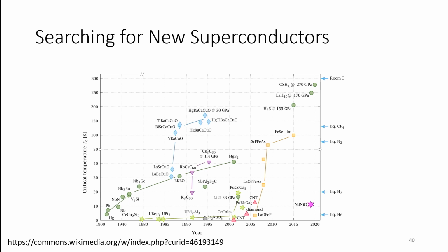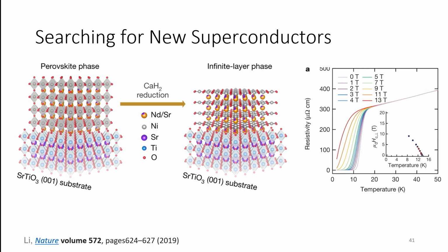So there's been a lot of progress over time, and there's been some really good work from the Mundi group here in discovering superconductivity in this nickel-based compound, which wasn't known to exist before. One of the tricks there was, neodymium nickelate has a perovskite structure I showed you previously. It was discovered at Stanford that if you reduce this, taking out some of the oxygens in some of the planes in the system, you can convert this material from being [insulating] into a superconducting phase with TCs close to 10 Kelvin.